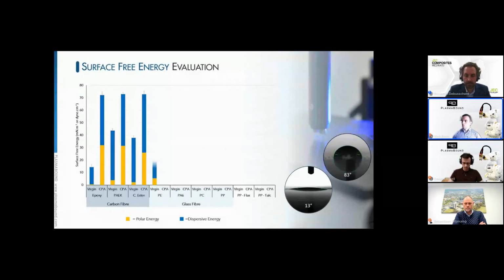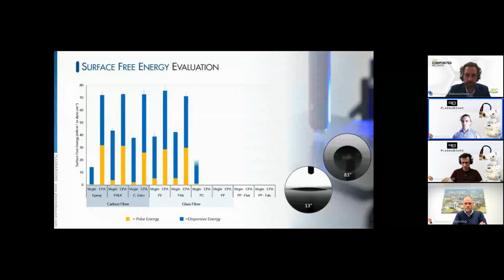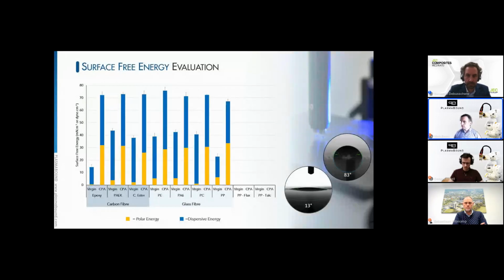When we look at the more commodity-based polymer systems with glass fiber around them, so polyester, polyamides, polycarbonates, and polypropylenes, we can see a very similar trend as well. So lower polar, that then after treatment is considerably increased, and then also an increase in the dispersive component. In some scenarios, a considerable increase.